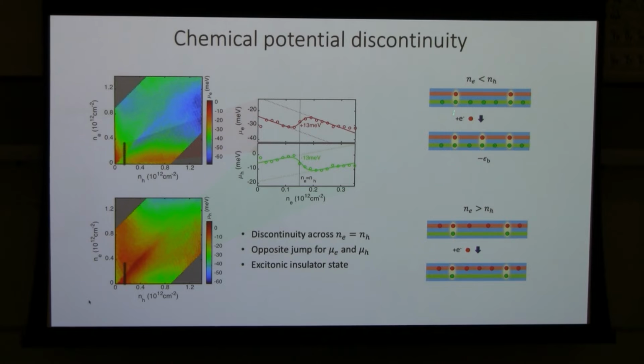To understand it, what happens is when the electron density is less than the hole density, we have excitons and also a lot of free holes. When you inject an electron into the system, it can always form a bound exciton, so it has low energy. But once you have an electron density larger than the hole density, when you inject an electron into the system, it cannot form an exciton anymore. It can only form a free electron. As a result, there is an energy difference that corresponds to the exciton binding energy.